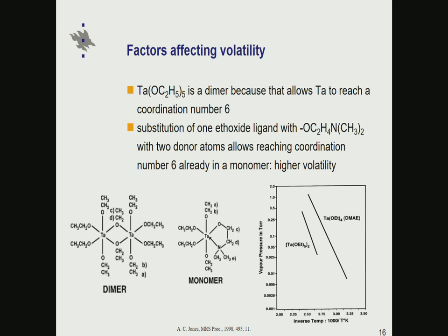Why it forms a dimer is that tantalum prefers to have a coordination number of 6 or perhaps even higher. If this would be just a monomer, the coordination number obviously would be 5. By making a dimer, both tantalum atoms are increasing their coordination number to 6, and they are happier in the environment. But that means the molecular weight for this dimer is doubled because of this dimerization.